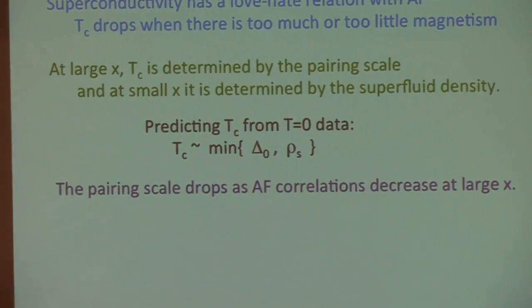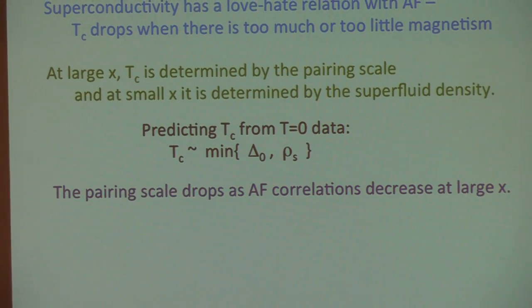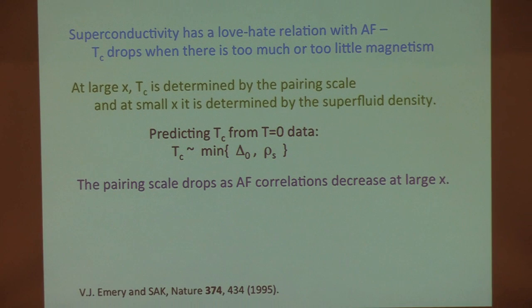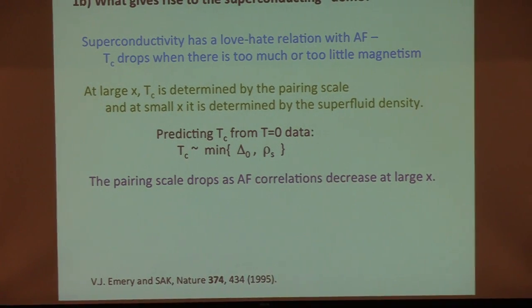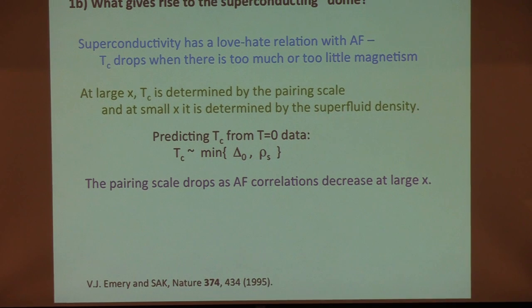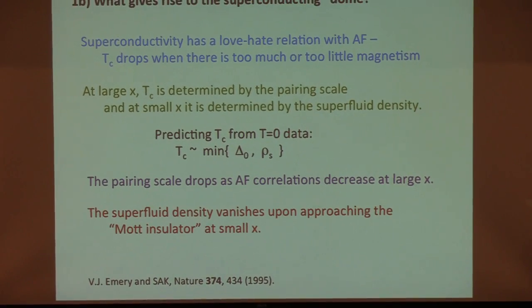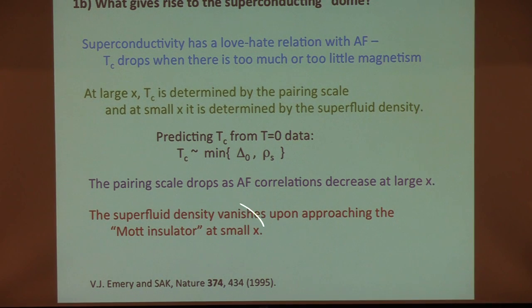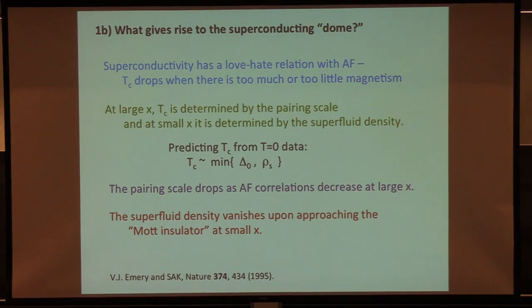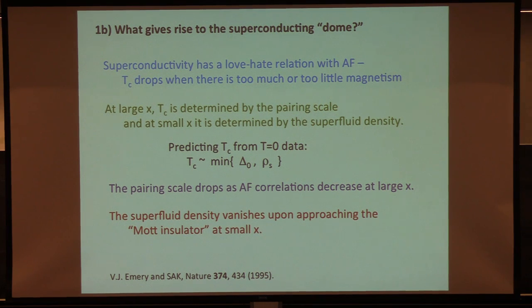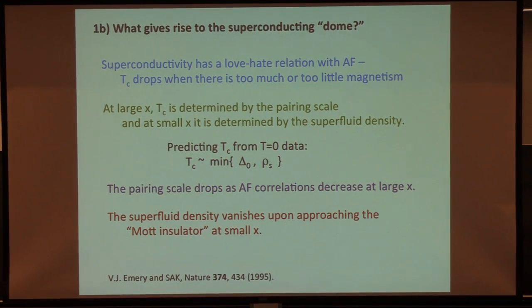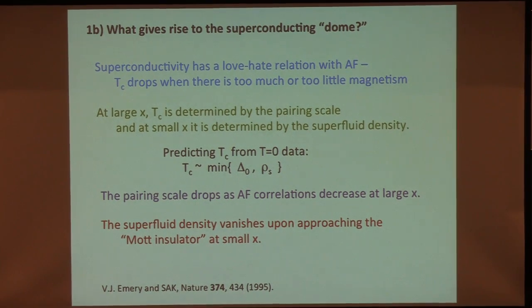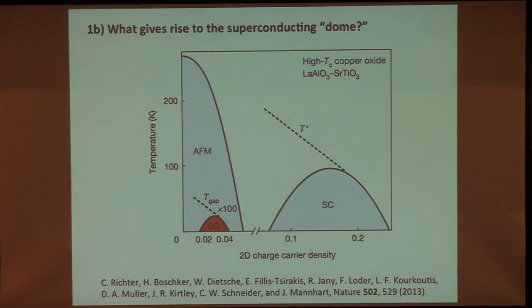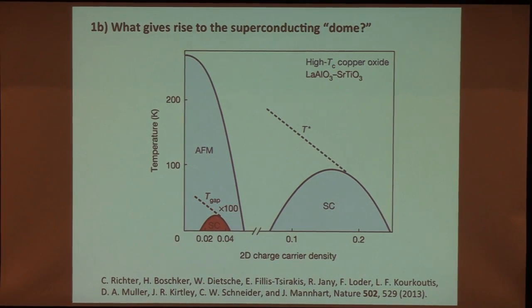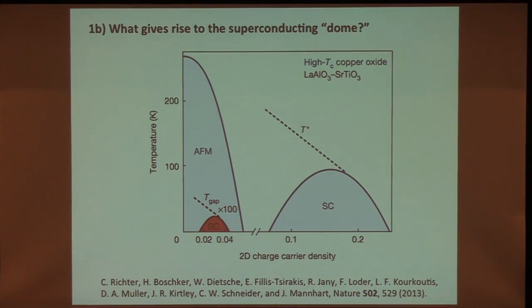It's a little more complicated in 3 dimensions in that it's not entirely determined by the superfluid density itself. But at least in many of the materials that we're going to talk about, since they're 2-dimensional, this isn't an issue. And so the superfluid density is directly an energy scale. Okay, and the point is that as we approach this Mott insulating state, since the superfluid density must vanish, then ultimately this thing must control superconductivity at low enough doping. And this is, of course, a very general proposition, especially for low-density 2-dimensional systems.